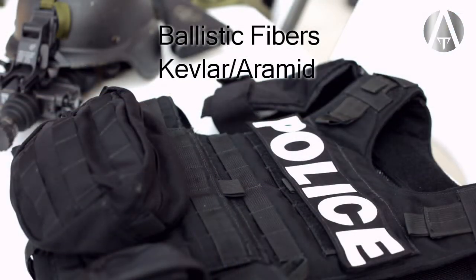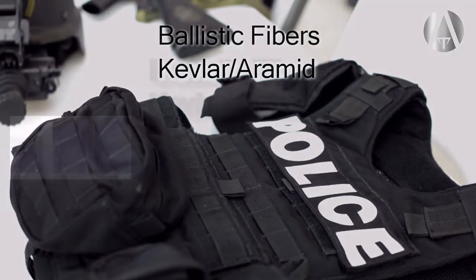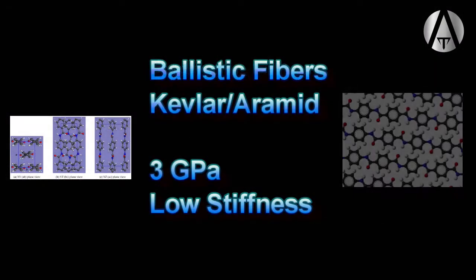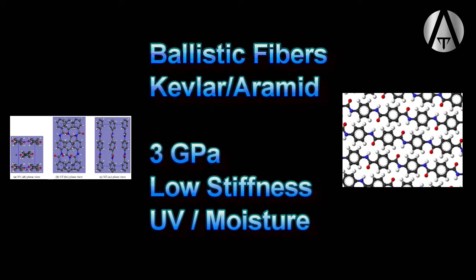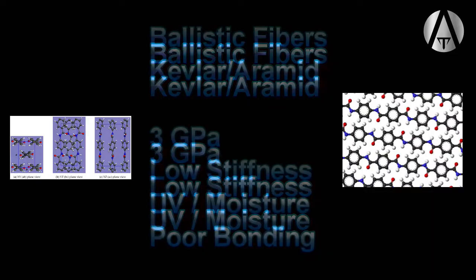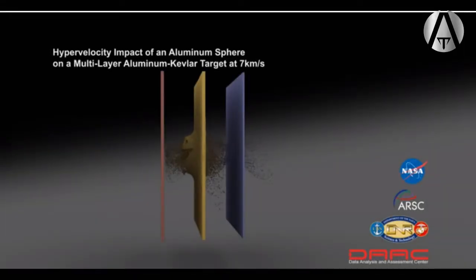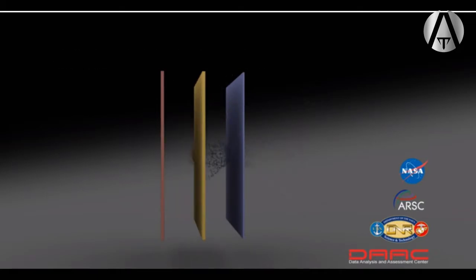Ballistic materials include fibers like Kevlar, usually called aramid in this application. Kevlar is well known for its use in bulletproof vests. It has a strength of more than 3 gigapascals with highly aligned linear polymer chains, but has low stiffness due to compression as these linear chains come apart easily. It is susceptible to ultraviolet light and moisture and does not bond well, leading to a weak but wear-resistant composite. The weak interface is useful for energy absorption, and it is used in bulletproof vests, military helmets, and impact protection on aircraft.